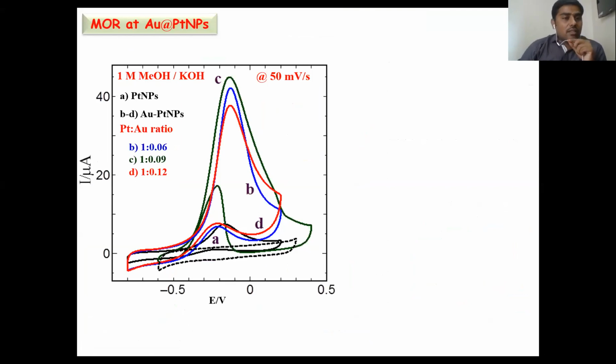The fabricated electrode is utilized for the electrochemical oxidation of methanol for fuel cell applications. Here, the platinum nanoparticles exhibit the methanol oxidation at minus 0.3 volt, and after the formation of gold platinum bimetallic nanoparticles, the bimetallic nanoparticles exhibited superior catalytic activity than the platinum nanoparticles towards methanol oxidation reaction.